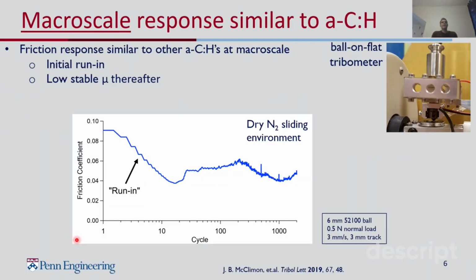So I'll start here with the macroscale response, which was obtained by using a ball and flat tribometer, like you see here on the top right, in a controlled sliding atmosphere. And so an example curve that we got here is what you see in the graph. On the y-axis, we have the friction coefficient. On the x-axis, we have the sliding cycle number. And the response that we see here is very prototypical for hydrogenated amorphous carbons.